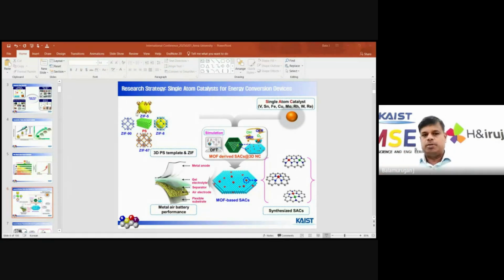When we use MOF-based material, we have to create some porosity using PS, which is a templating material, polystyrene. After pyrolysis, the PS is removed from the carbon networks, leaving an enriched carbon framework, and the single metal is easily attached to nitrogen and bonded with the graphitic carbon networks. We can use different types of single-atom materials: first-row, second-row, and third-row transition metals. Compared to the first row, the second and third rows are very high in cost. But the second- and third-row materials can be used for acidic media, while the first row can be used for basic media.